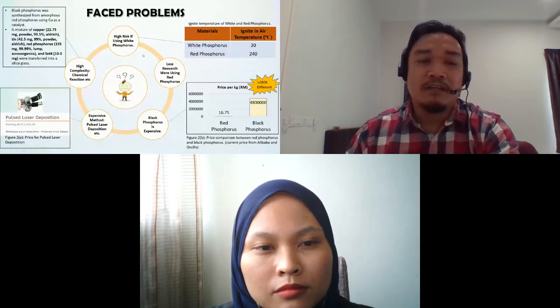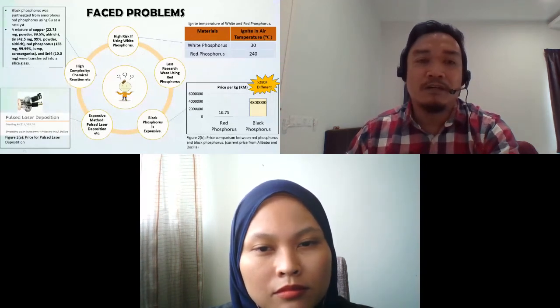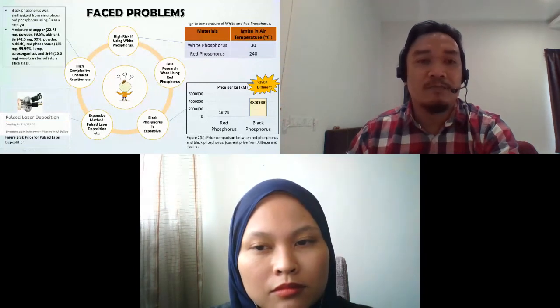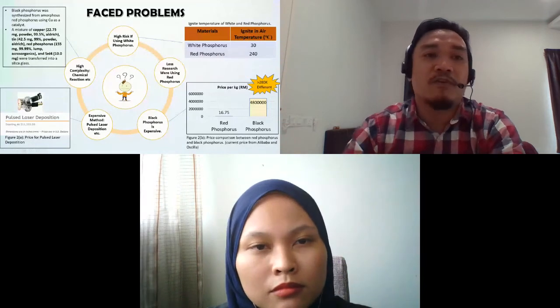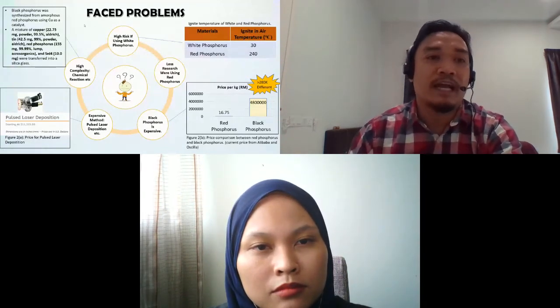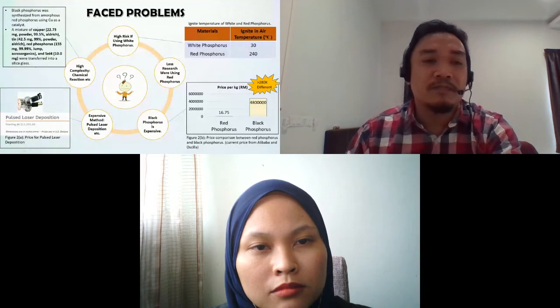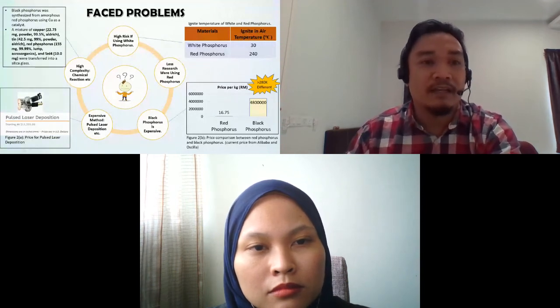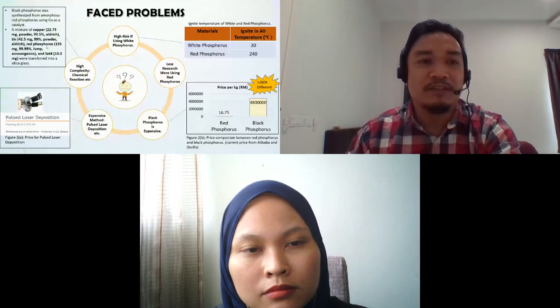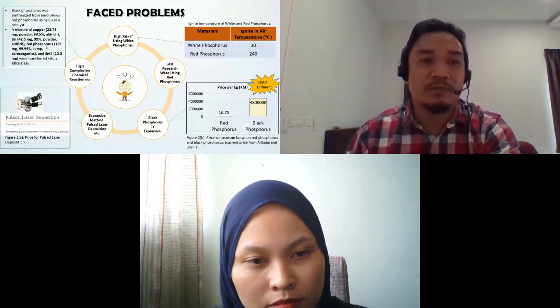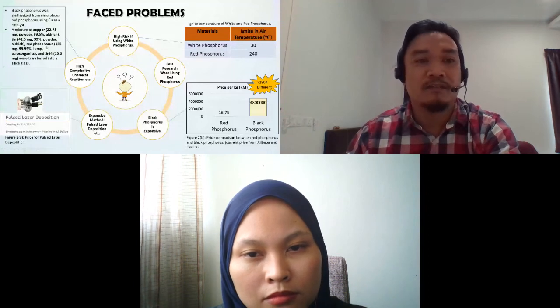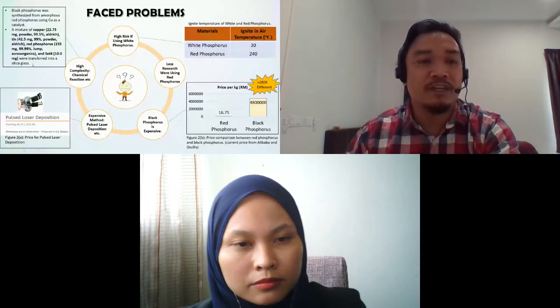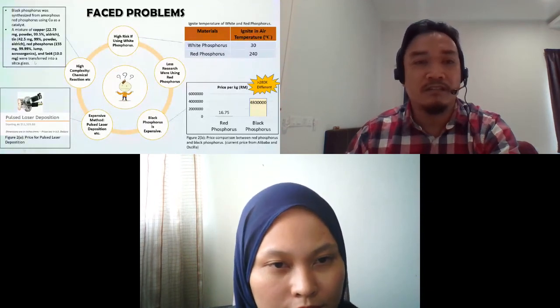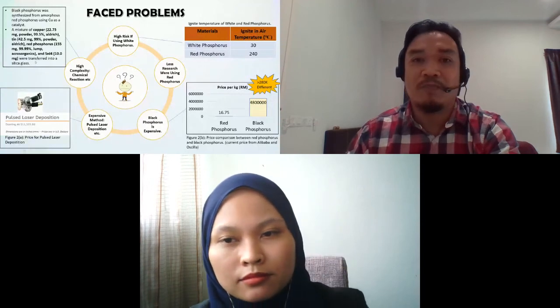First one, the synthesis method has very high complexity. Black phosphorus was synthesized from amorphous red phosphorus using copper as a catalyst. They add something like this, a lump, and it is very complex here. And finally, we transfer into a silica glass. That one is very complex. We don't talk about the parameters yet. We need to control the atmosphere, the temperature, the humidity, which is very complex.